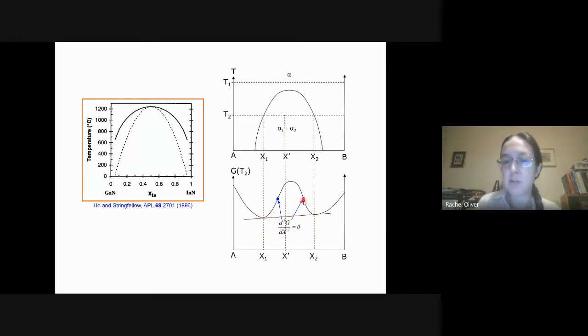Now, those points of inflection are important because if we're within the part of the curve defined by those points of inflection, then if we start off with material at X dashed and it just decomposes just a little bit into slightly more A-rich and slightly more B-rich material, we'll instantly lower the energy. That means that as soon as the decomposition starts, the energy gets lower, and that means that decomposition can happen really quickly. So fast decomposition occurs within this dashed line, which we call the spinodal.